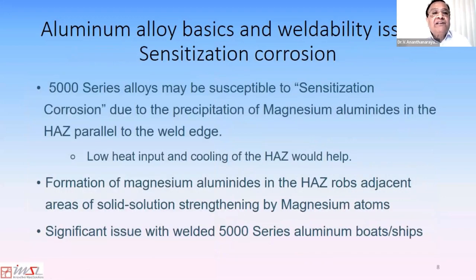The aluminum alloys also are subject to sensitization corrosion, particularly the 5000 series alloys, which happens due to the precipitation of magnesium aluminides in the heat affected zone parallel to the weld edge. There is a temperature range in the heat affected zone that is favorable for the formation of these magnesium aluminides parallel to the weld edge in the heat affected zone.